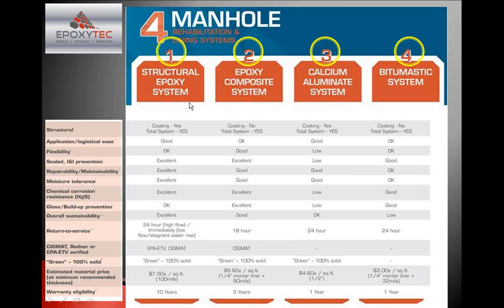And now let's look at system number 1. This is the structural epoxy system. This one would be used in the most treacherous conditions. I always use Florida as the example. Florida became a training ground for a lot of our products, and it's actually good that it had, because if we can solve it here, we can pretty much solve it anywhere. We have the worst of a lot of things. We have no elevation, so we have almost zero gravity, which means that our sewers are stagnant, our water stands a lot, so we have very high hydrogen sulfide buildup in most of our structures. Adding to that, the heat throughout most of the year intensifies the hydrogen sulfide buildup, so we have very, very high parts per million hydrogen sulfide in our wastewater infrastructure system.